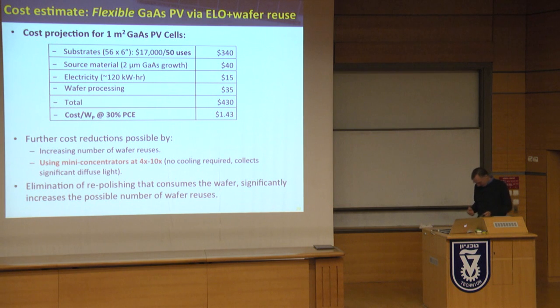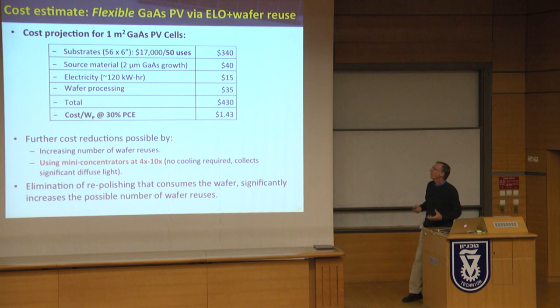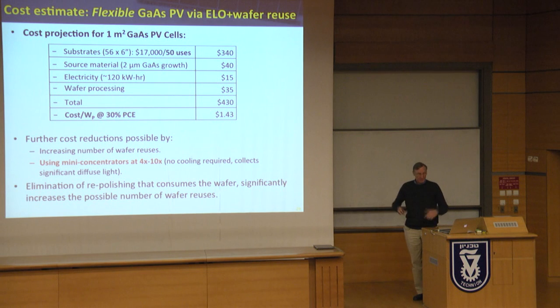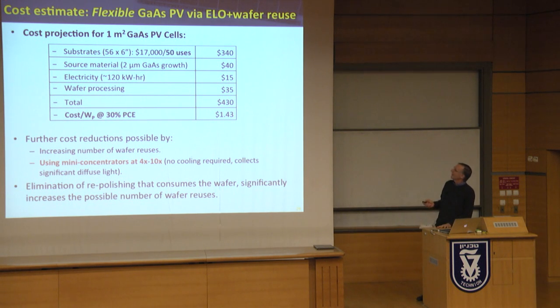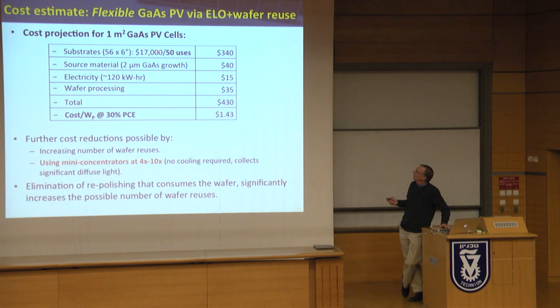This is not careful or comprehensive modeling of the economics, but here we started out, we tried to be really aggressive on the cost that we're going to order barrels of gallium arsenide wafers, so we said it's only $17,000 per meter squared, and that's 56 6-inch wafers. You have to square them up because you don't want to waste any material, and that comes to $340 per square meter if you can reuse it 50 times. If you have absolutely no damage, you should be able to do that.